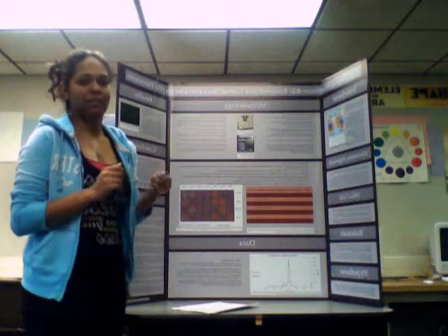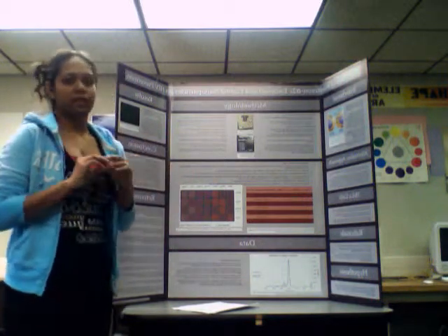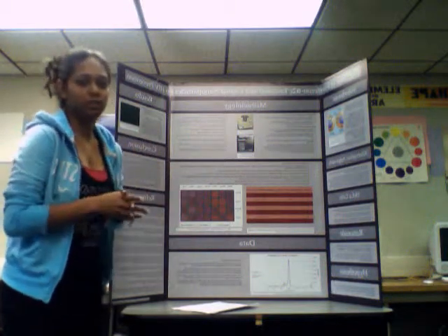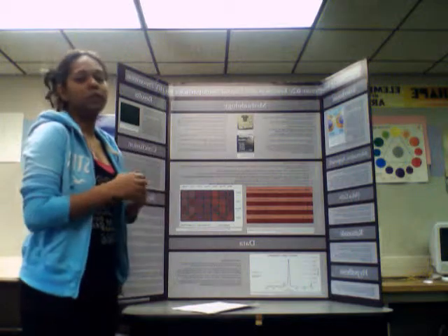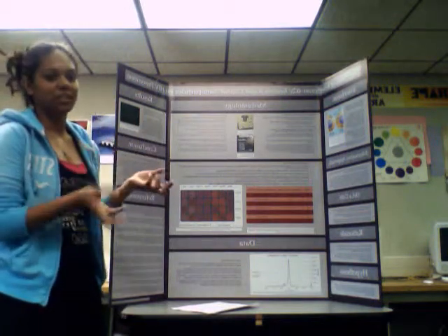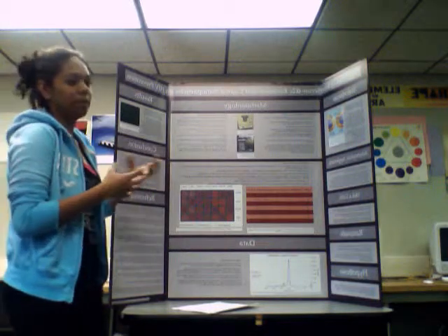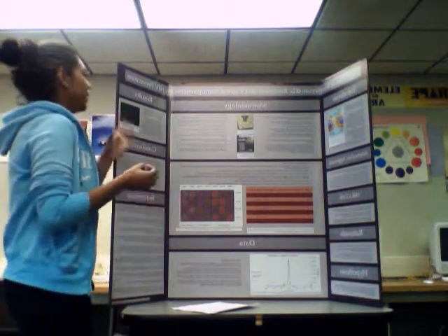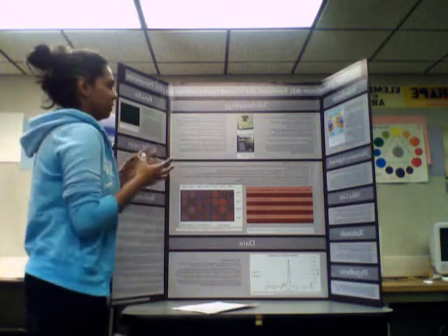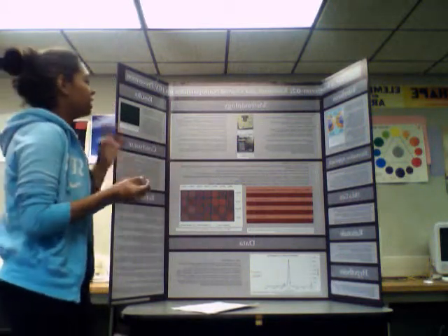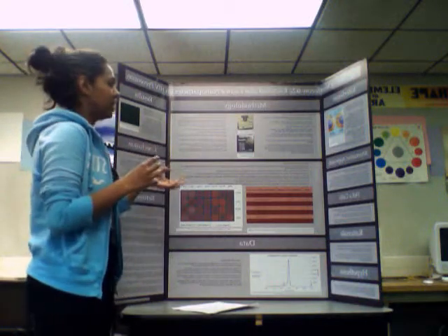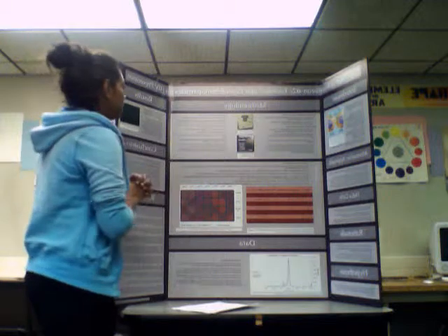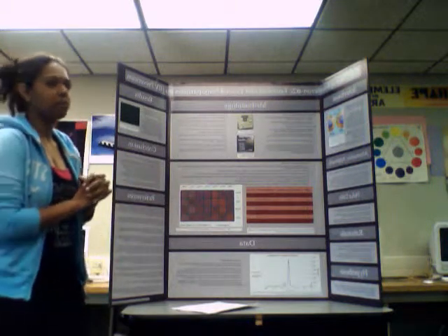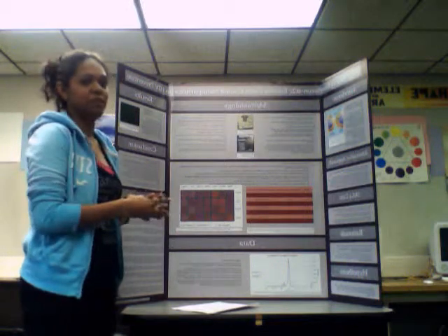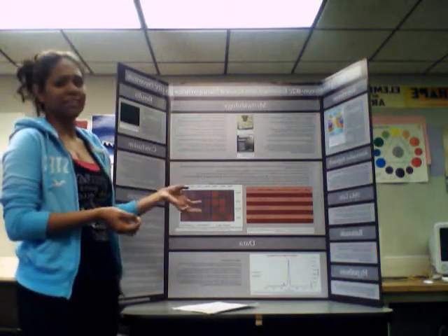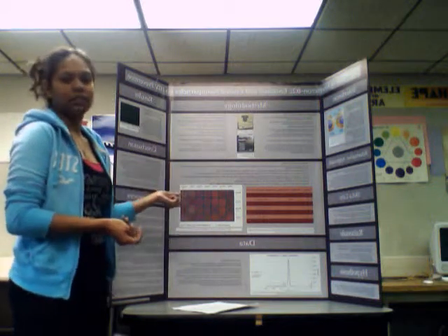Upon drying, the powder was then ground up, and the blank nanoparticles were placed at room temperature for storage, and the interferon enclosed nanoparticles were stored at -80 degrees Celsius to prevent degradation of the protein. Now, the third sample that I prepared was interferon-coated nanoparticles. This sample was actually prepared on ice, again, to prevent the degradation of the protein. First I took a sample of the previous blank nanoparticles created. I washed it in PBS solution, and I set it to incubate with 50 micrograms per milliliter of interferon for 1 hour at 4 degrees Celsius. The final sample and the supernatant were then stored at -80 degrees Celsius.